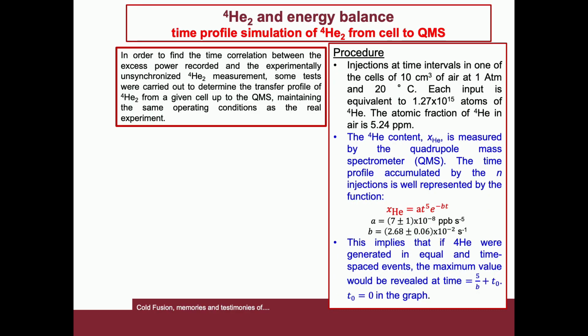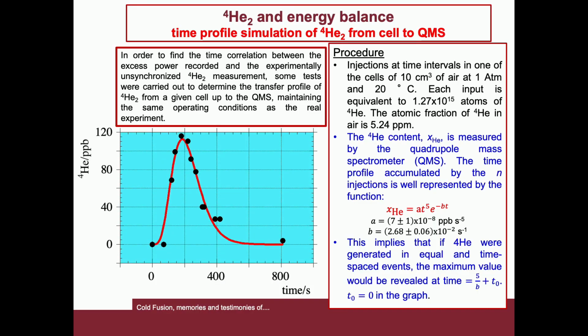The procedure consisted of injection at intervals of time into one of the cells of 10 cubic centimeters of air at atmospheric pressure and at 20 degrees C. The input is equivalent to 1.27 × 10^15 helium atoms. The atomic fraction of helium in air is 5.24 parts per million. The helium content is measured by the quadrupole mass spectrometer. The time profile accumulated by the injection is well represented by this function. This implies that if helium were generated in equal and time-spaced events, the maximum value would be revealed at the time given by this relationship, where T0 is equal to 0 in the graph.